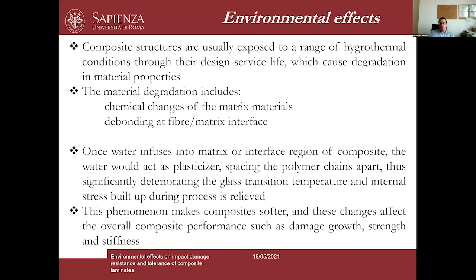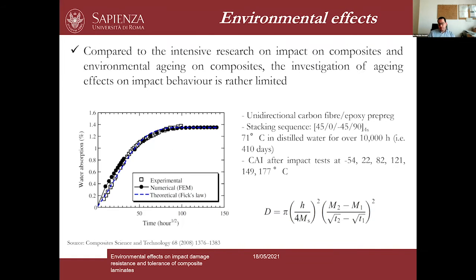And these hygrothermal conditions can cause, for example, chemical changes in the matrix material. They can, for example, destroy the fiber matrix interfacial adhesion. And so it is expected that these effects can completely change the mechanical response of composite materials, not only the post-static performance, but also the dynamic response.